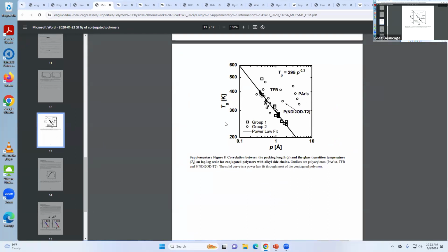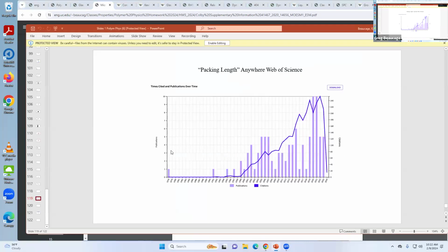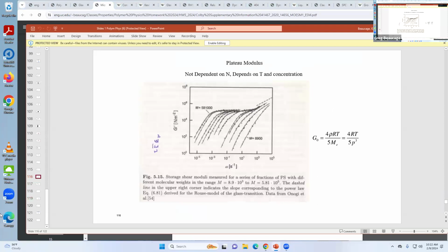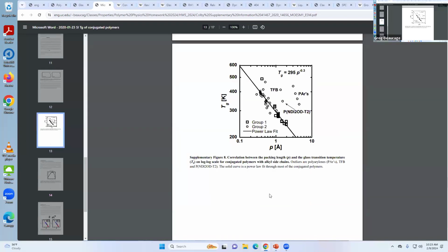They don't mention that in the paper, but the -3, if you look back to the notes, you find this is the storage modulus. At low frequency, it's a liquid. Then you reach the rubbery plateau where it's a rubber, and then it goes into some other stuff about the rotation out here. It's in a tube, so it flows again. That's the idea. So once you reach a tube diameter, then other things happen, right? So you have the rubbery plateau, that's the plateau modulus, and that goes with 1/p cubed. He doesn't give the slope in this either, but I replotted this and figured out the slope is -3.3.